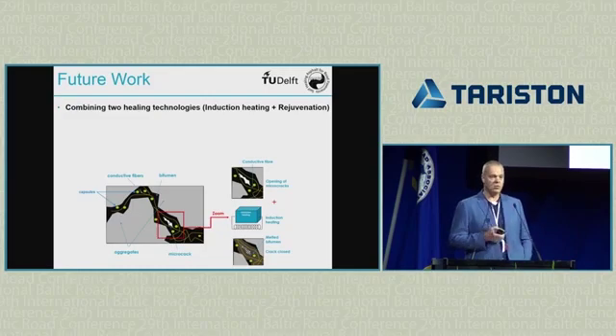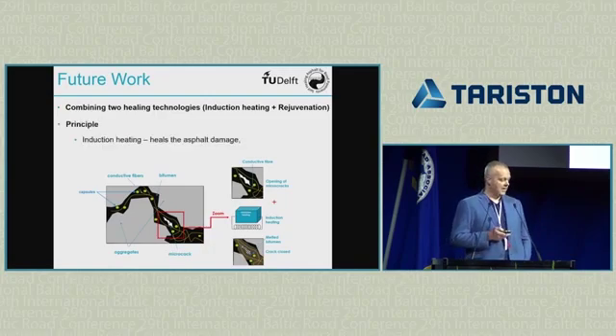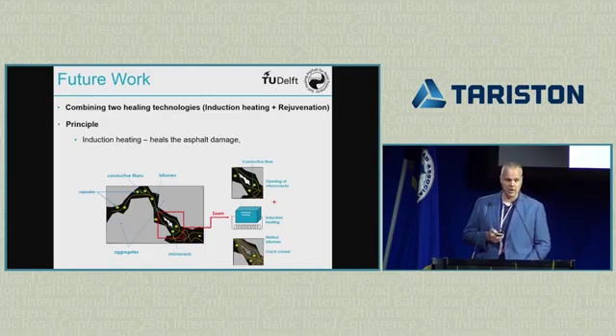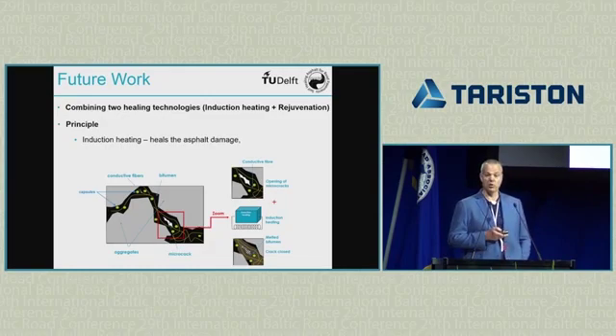So with the induction energy, we put the steel fibers in there, we put the capsules in there with rejuvenator, so we can heat up the road with the induction energy, heat up the fibers. This will melt the bitumen, close cracks, and also open the capsules with rejuvenator, which then rejuvenates the binder. Since the binder is warm, the diffusion goes very fast, and everything should be perfect after that. So that's what we are trying out now in the lab, and that also shows very good results up to now. So combining the two techniques, that's the future.